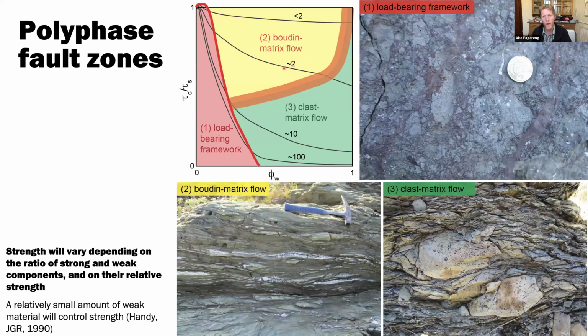So you end up with three end member behaviors. If you have the strong rock with pockets of weak rock that are not interconnected, the load-bearing framework of strong rock dominates. If you have relatively similar strengths in a viscous system, you get some boudins of the stronger phase in the weaker phase. They act as a composite, and their strength is a rough average. Whereas if you have a dominant matrix flow, then you're seeing a bulk strength that's close to or even equal to the strength of the matrix. So that's the bulk effects.